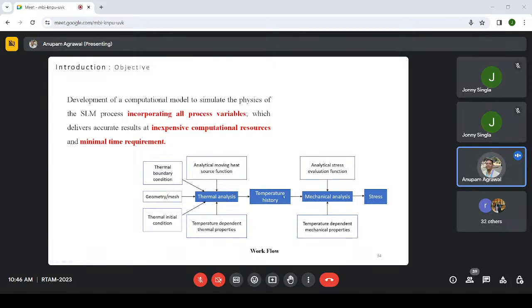Based upon the thermal analysis, we have predicted the temperature history of the part for different laser scans, different laser scan velocities and different laser parameters. Then based upon this temperature history, we have conducted the mechanical analysis to predict the stress evolution, the residual stresses, and also the mechanical properties of the final part. So we have done this in these stages: the development of a computational analytical model to simulate the physics of the SLM process, incorporating all process variables, which delivers results at inexpensive computational resources. This is an analytical model which does not take much computational time to predict the results.